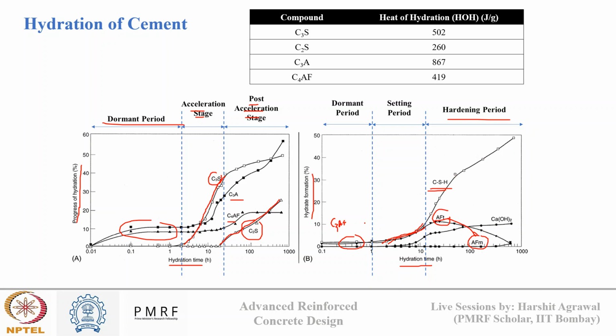Now these hydration reactions that we talked about in different equations are exothermic reactions. Okay, and these different compounds C3S, C2S, and C3A liberate different amounts of heat upon hydration. So if you see this table at the top, it lists the heat of hydration in joules per gram of compound undergoing hydration. So you see C3A releases the maximum heat during hydration, followed by C3S, then C4AF, and then C2S. Okay, so this is the rate at which heat is released per unit consumption of these compounds when they react with water. And this is known as the heat of hydration.